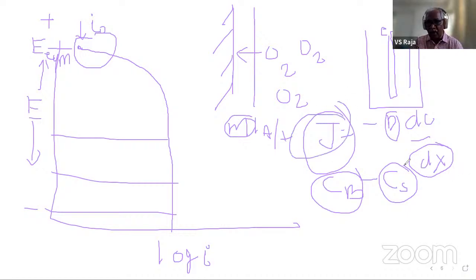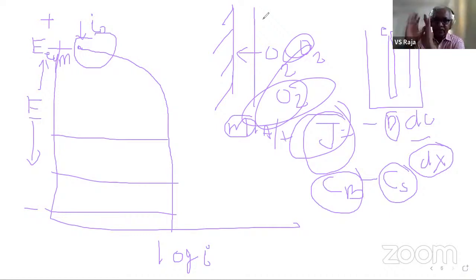How do you lower the thickness? I do agitation, I do stirring. When I do stirring, what happens? This layer becomes thinner because the convection pushes the oxygen molecules to the surface. So this becomes smaller now. So the limiting current density will increase as you do agitation more and more. Okay, I hope that you have an idea now about what is meant by the limiting current density.